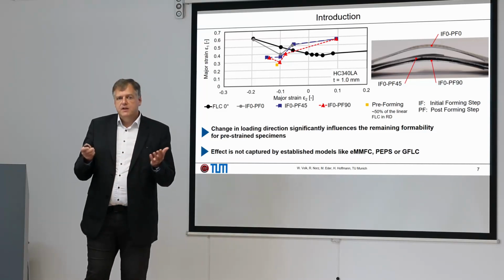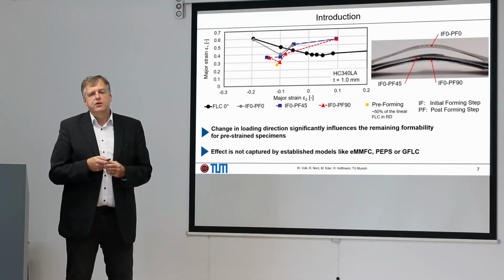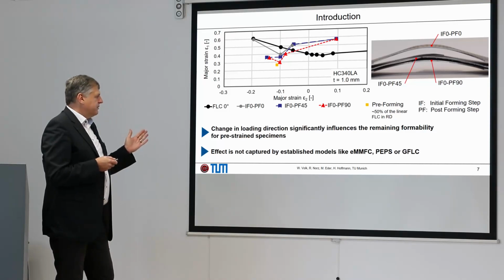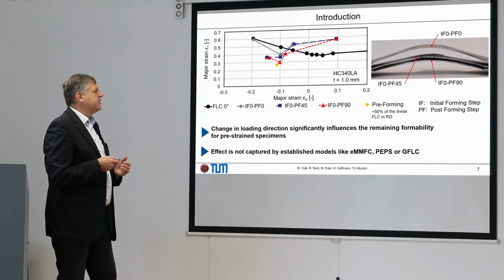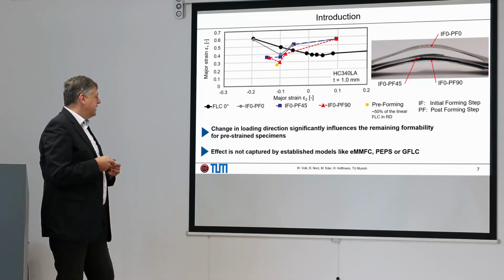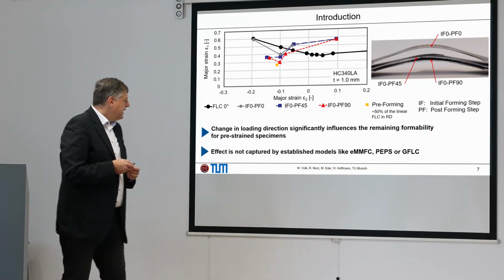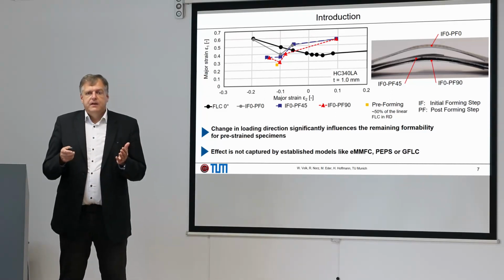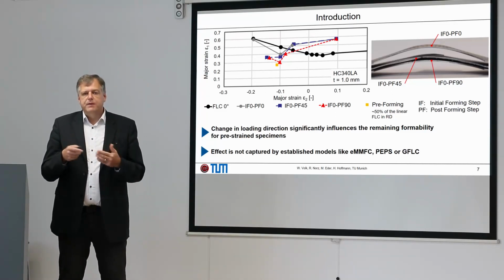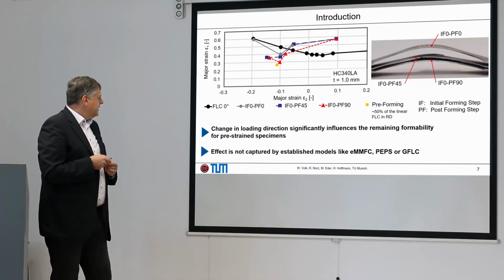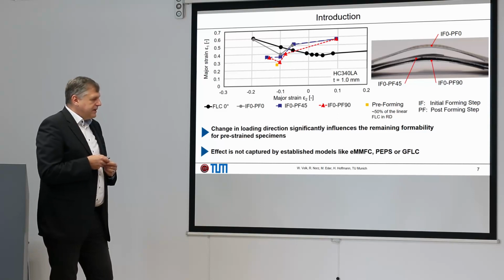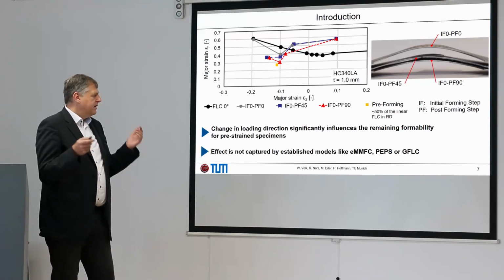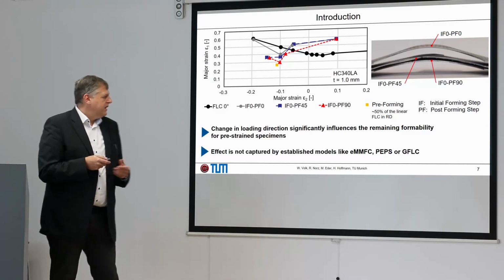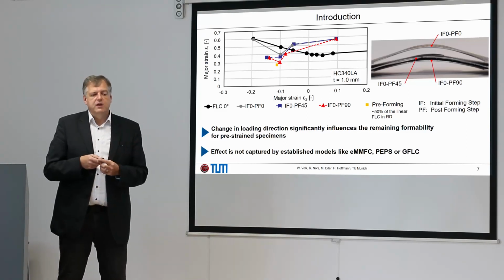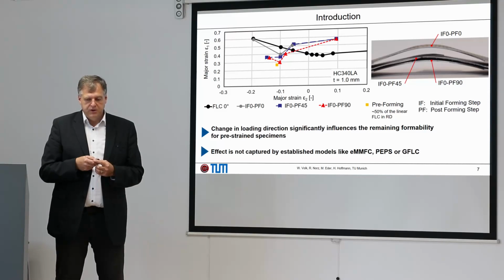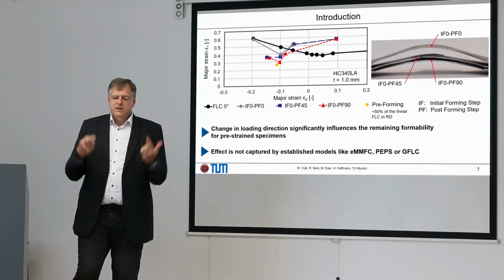So I want to summarize this as the fundamental motivation of the paper, that a change in loading direction surprisingly led to a significant influence on the remaining formability for pre-strained specimens. And due to the fact that the stresses are probably the same, we can directly find out that this effect cannot be captured by established models which are published and used, like the eMMFC, PEPS, or also our phenomenological GFLC model. So now we go more in detail.